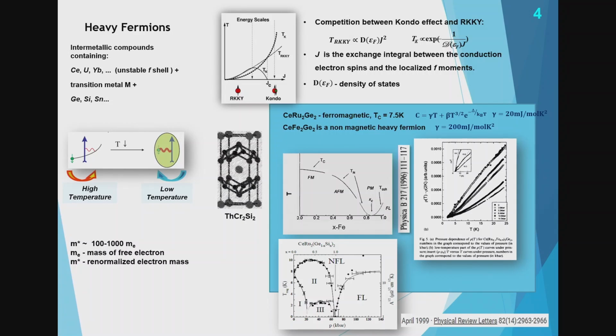And on the other side, I did a study with the introduction of iron in this material here. So the parent compounds are this and this. And this system is non-magnetic and is already a heavy fermion with a very high value of gamma, of the Sommerfeld constant. And then in my work, I made the phase diagram of this system, showing that doping with iron the cerium, ruthenium-2, and germanium-2, we go from a ferromagnetic system through an antiferromagnetism, and go to a quantum critical point, okay?